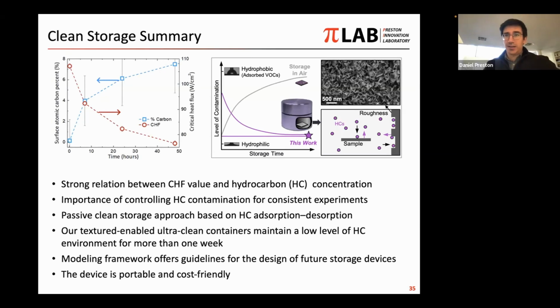And we developed this modeling framework, which first of all predicts the behavior that we observe experimentally quite well. And second of all, allows us to then probe this design space when we want to create future types of storage devices. And we found that this was portable. We could store it before use for maybe a month or more, and relatively cost-friendly or low cost. So this is just aluminum containers that you can buy from Amazon or online.